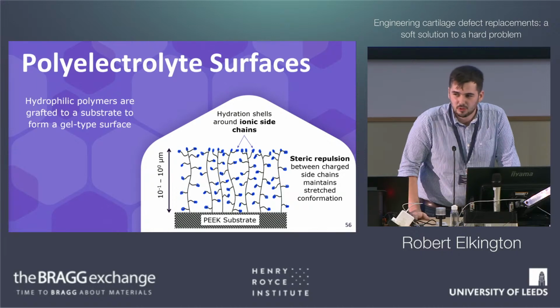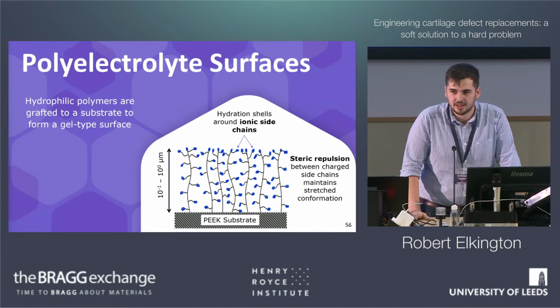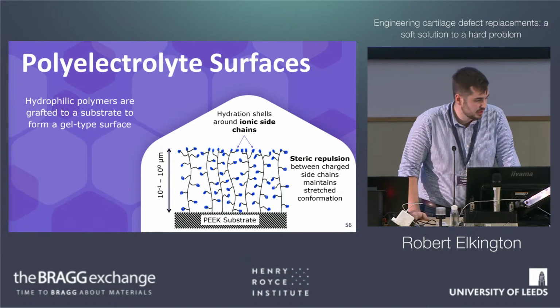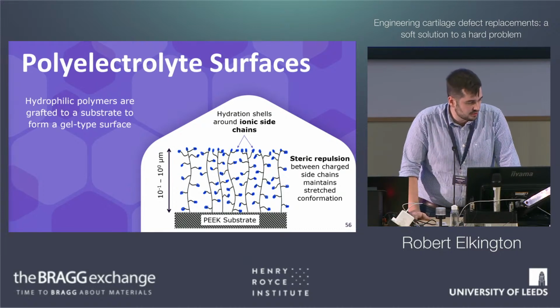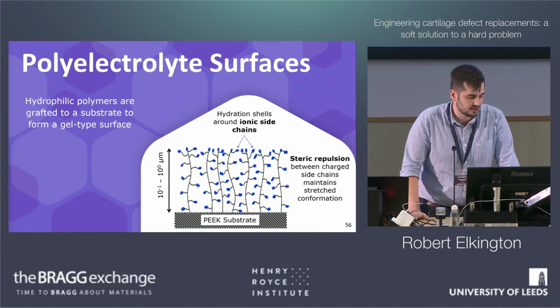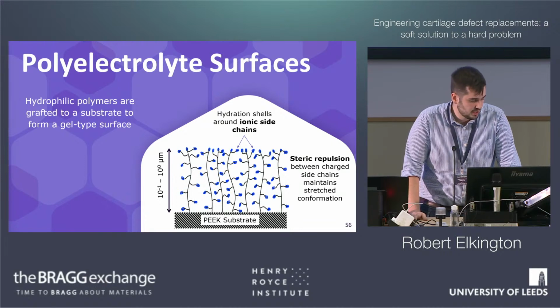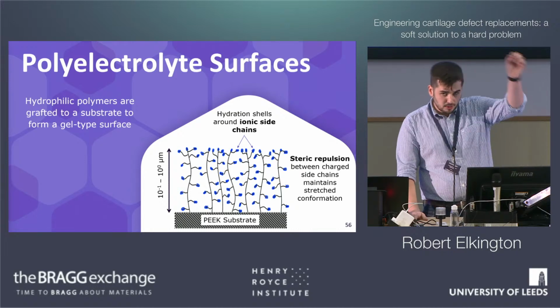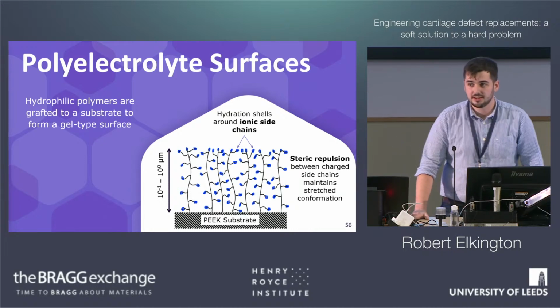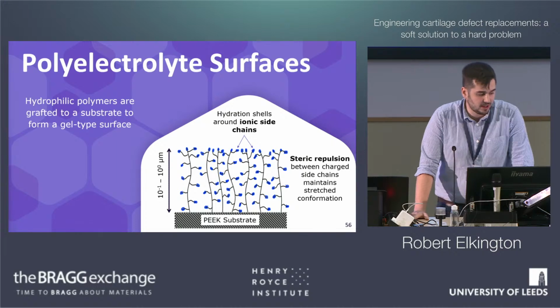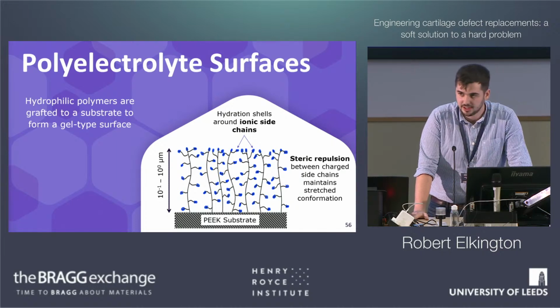Conceptually, it's quite easy to think about as an uncross-linked hydrogel. That's how I like to think about them. These are hydrophilic polymers grafted to a substrate, so they're engrafted. They're pretty thin, on the order of microns, and you have some polymer backbone, and on the side chains you have functional groups, and for our purposes, these are charged functional groups that